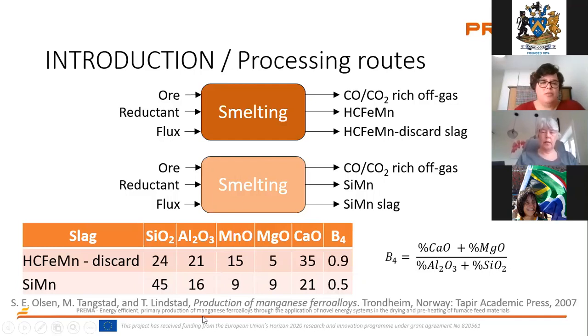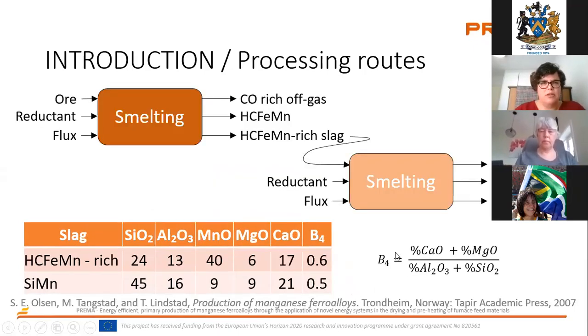So here you see the composition of the slag, and what it's mainly driven by is that our ores are rich in carbonates, and that's why we have such a high CaO content. Calcium carbonate and also dolomite. And I see my colleague Triti is also part of the audience today, and she's a total expert on this. So if anybody wants to know more about manganese, there's just a way to go. But you'll notice the basicity of the discard slag in practice is 0.9 and 0.5. Remember those numbers when we go to the next slide.